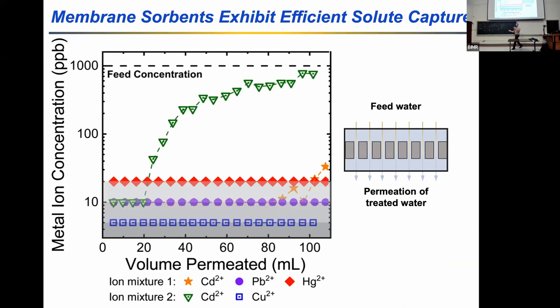But we can also do breakthrough curve experiments with these thin film membrane adsorbers. And so we've got two solutions here. One that's a mixture of cadmium, lead, and mercury. And we don't see any of those metal ions in the permeate, at least based off of our capabilities with ICP-OES and our limits of detection. For the cadmium and copper, I like that best because we never see copper come out in the permeate because it's got a huge affinity for the terpyridine moieties.